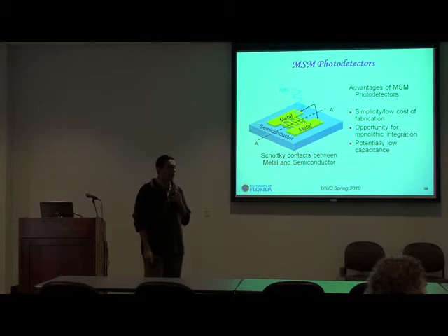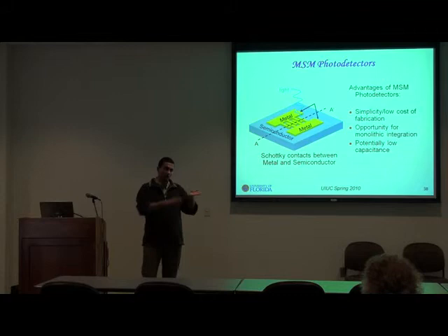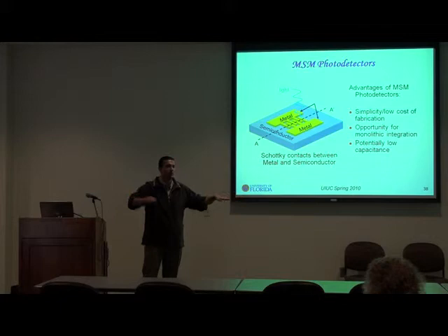So this 1/f noise of course goes down as we increase the frequency, but then there's a noise floor, the thermal noise of this material, which just depends on the resistance. It's from the fluctuation of the carriers that we generally have in any material, even if you measure a single resistor. That only depends on the resistance, and it's always there as a flat, like a white noise. So eventually that 1/f noise goes below that, so you just see that. So you were seeing that.